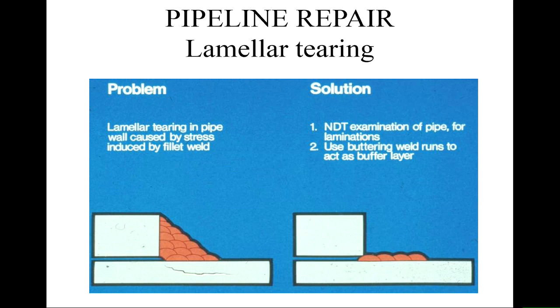So what you tend to do to solve these problems of lamellar tearing, you've got a residual stress in here. This is contracting as it cools, and that puts a contraction stress on the top part of the metal. If there's any of these little defects, then you get these lamellar tearing cracks. You're going to have to do some non-destructive testing of the region around where you're going to weld to look for any potential lamellar tearing defects that are already present in the material.